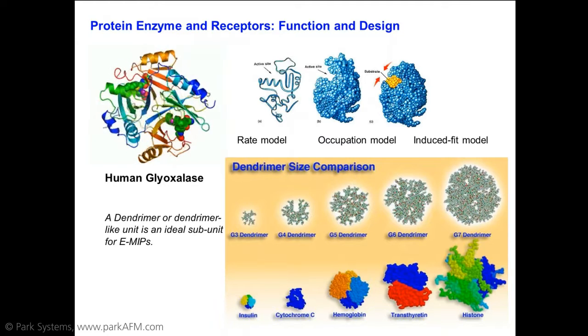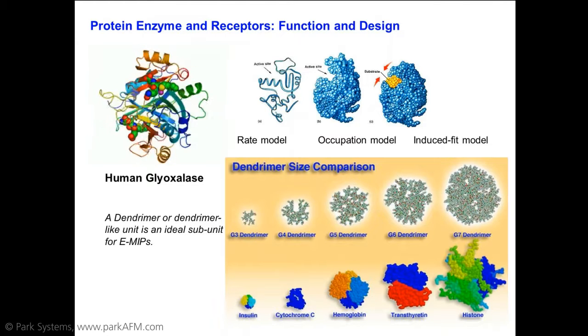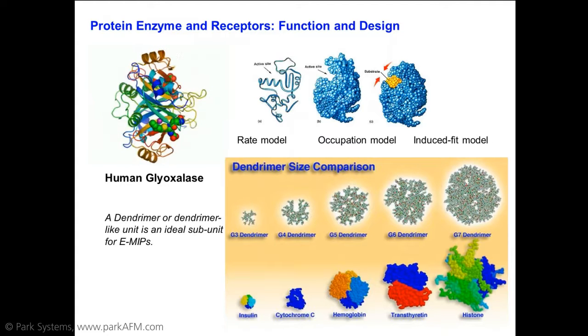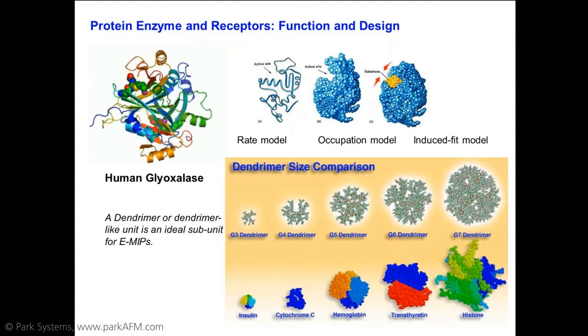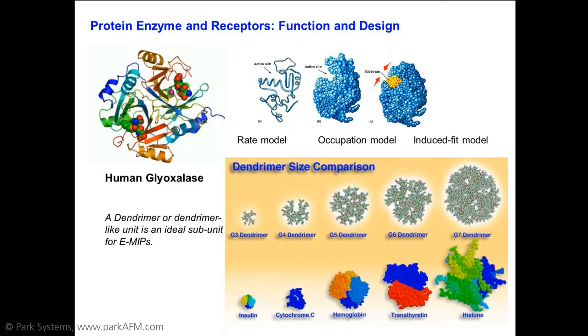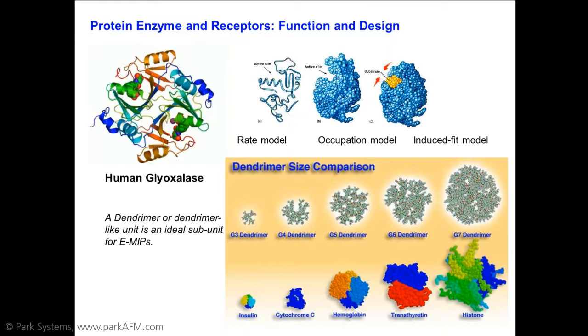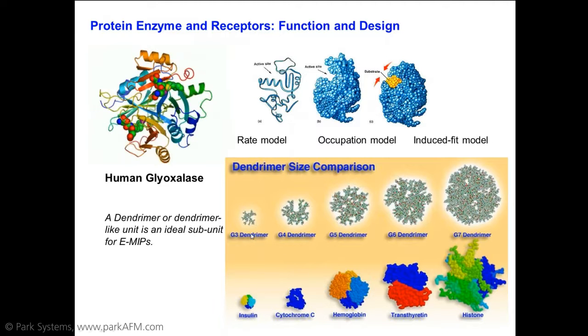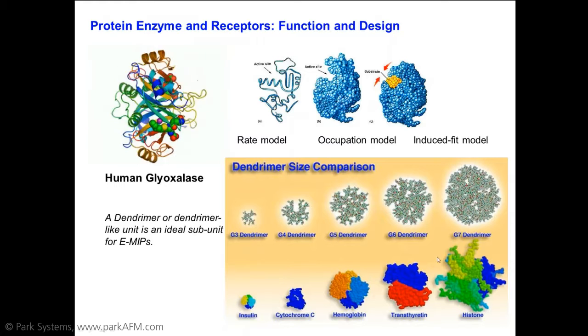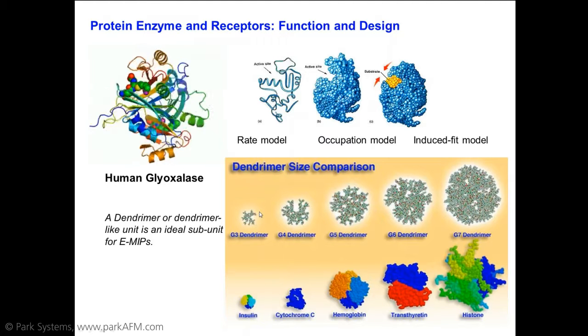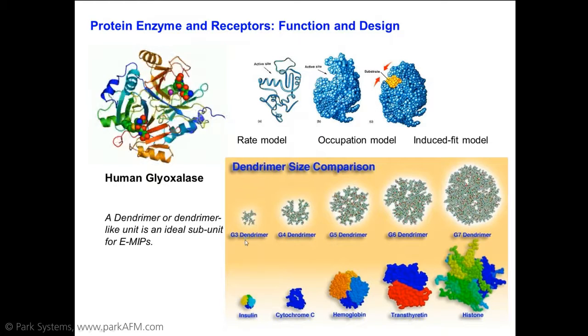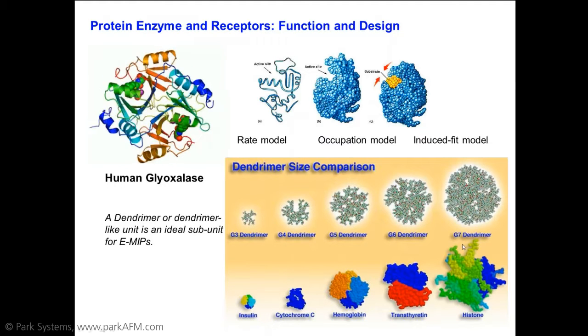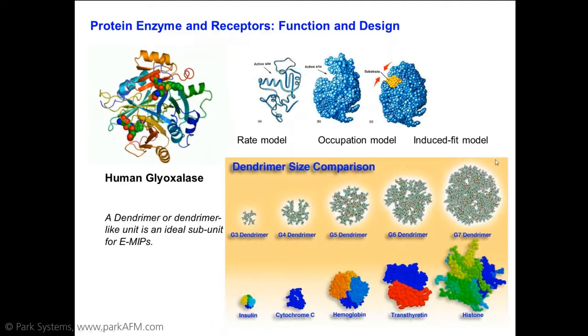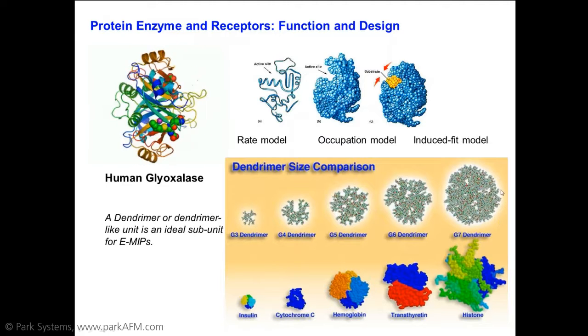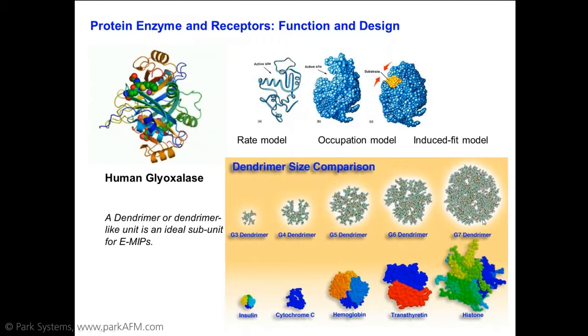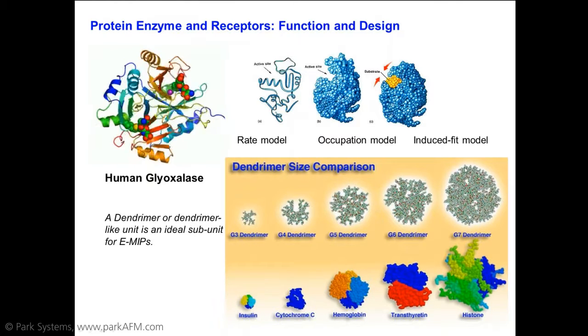That means that you have to have some specificity in these interactions, and there has to be an advantage in terms of the signal that is generated upon this synergistic interaction. Now, in the lower part, I show here a comparison of dendrimeric size, which is basically a hyperbranched polymer or macromolecule, in which the generation or the size goes from G3 to G7. So exponentially, you can see the increase in the size and the amount of functional groups as you grow a dendrimer step by step into a larger macromolecule.